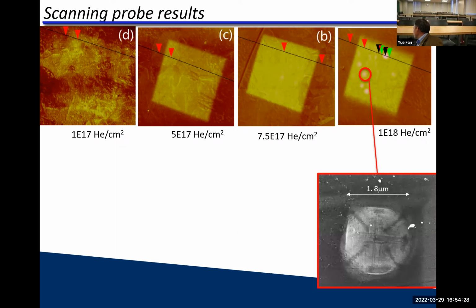And so one of those features actually looks something like that. So these are like little domes popping up. Now, interesting features to note, they actually have this X shape, and then they have a second X here. They have 2 X's in there. Now, the dark X comes from the fact that this was a single crystal copper, and when it bends, you end up getting channeling contrast, specific crystallographic directions. And so that's what we see here. These, however, are probably slips from the surface because it had to undergo some plastic deformation.